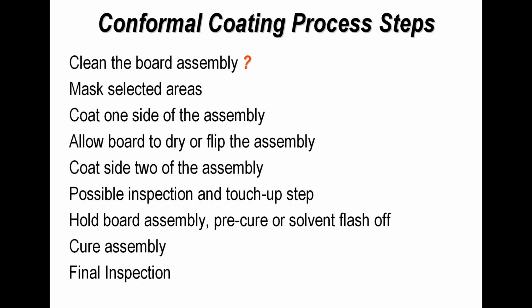If you take a lot of automotive manufacturers, the majority of those do not clean, however they do conformally coat. However, they must engineer their process to minimize the amount of contamination which is present from any previous soldering operations. The next step is masking selected areas depending on the design of the printed circuit board, and then we would coat side one of the assembly, possibly allow the board to dry or touch dry prior to flipping the assembly over. If it's an automated process and you're spray applying the coating to the surface, then you would probably flip the board assembly over and continue coating the second side.